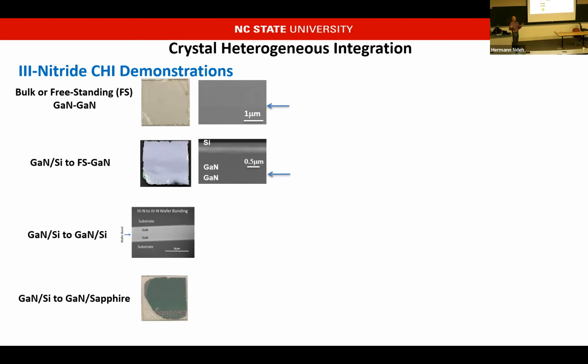And one of the key things that we found when we were doing the LED work is that one of the most stringent things you can do to test the strength of a wafer bond is to saw two wafers. That's even more stress than thermal shock or all kinds of packaging. And so we're able to readily saw all of these things here on the gallium nitride to gallium nitride bond. We're also able to bond gallium nitride on silicon to freestanding GaN, even despite the thermal expansion mismatch in silicon. Again, you can see the bonded interface here: GaN on silicon, GaN on silicon, and most challenging, GaN on silicon and GaN on sapphire.